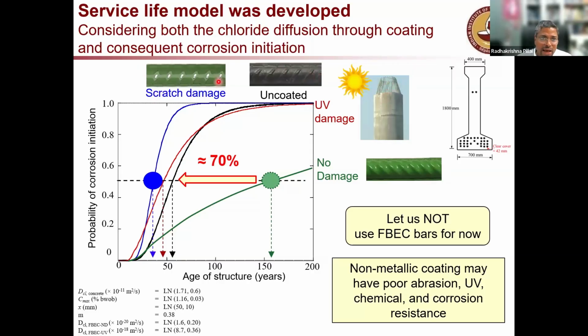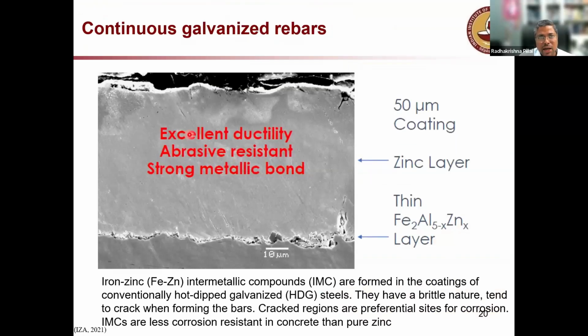And then if you have a scratch damage, the blue curve here, this also will lead to the same. If you have scratches like this, it will start corroding. And it is essentially a crack, a wide crack. So when moisture gets in there, you have chances of crevice corrosion on those rebars. So essentially the message here is that there could be significant reduction in the anticipated service life if the surface coating is damaged, either by mechanical damage or UV induced damage. Okay, if there are cracks or scratches on the epoxy coating, it's better not to use that. Okay. Now, another thing which is coming up in the market now is something called continuous galvanized rebars.